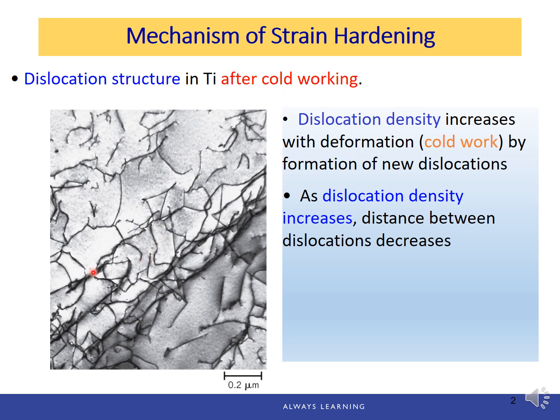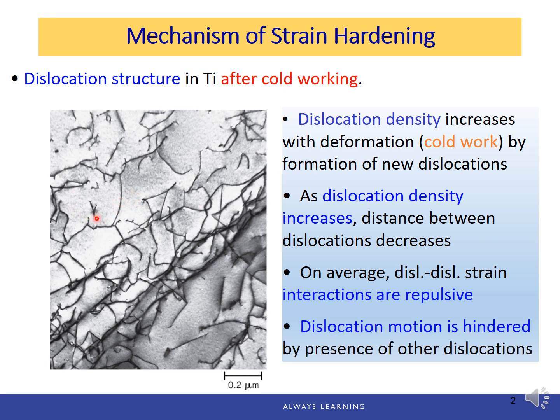The dislocation density increases with deformation by formation of new dislocations. And as dislocation density increases, distance between the dislocations decreases, which means the dislocations are close to each other. And on average, the dislocation strain interactions are repulsive. So because of that, the dislocation motion is hindered by presence of other dislocations. Therefore, the material will be strengthened.